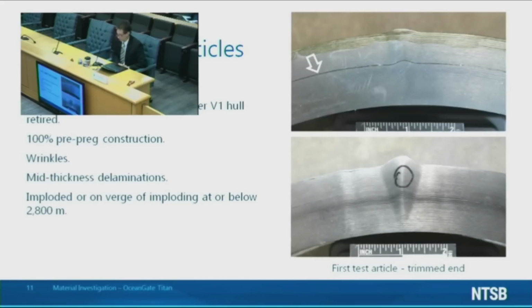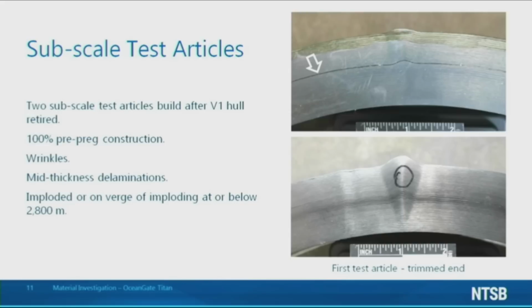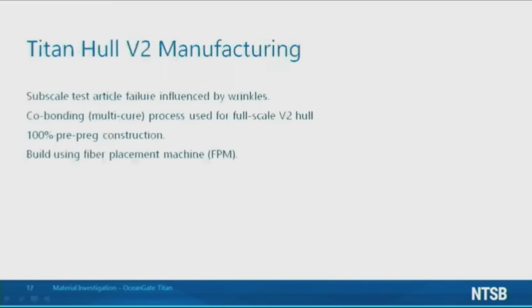The trimmed end piece contained two notable wrinkles and a mid-thickness delamination, as indicated by the arrow in the upper image. According to multiple former directors of engineering for OceanGate, both subscale test articles imploded or were on the verge of imploding at or below 2,800 meters. OceanGate identified these wrinkles as a likely cause of the low implosion pressure. In order to mitigate the wrinkle problem, OceanGate pursued a co-bonding process, which I'll describe in a couple of slides.